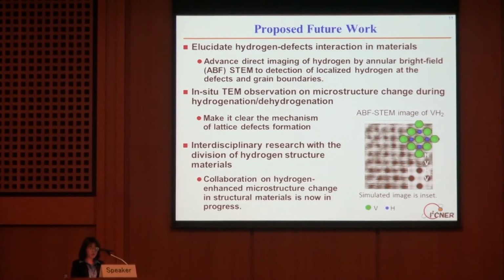We would like to advance the annular bright field STEM method for detecting localized hydrogen at defects and grain boundaries. ABF STEM enables us to observe hydrogen directly in metal hydrides. This is an ABF STEM image of vanadium hydride. Gray points indicate hydrogen columns. In situ TEM observation is a little bit difficult, but it can make clear the mechanism of lattice defect formation.